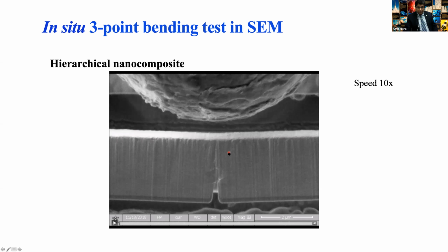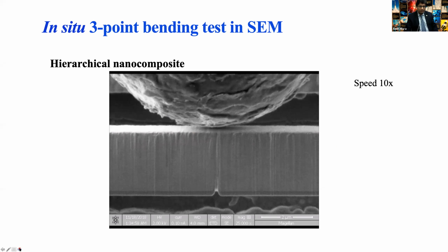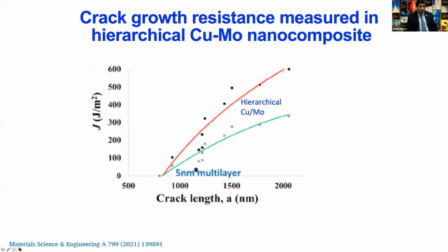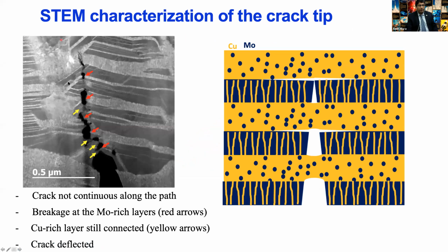So what we do is, when the test has stopped, because the sample did not fail, we section this with FIB and take the foil out and put it in TEM. That is shown in the next slide here. So this is one way where we can track it. This is how the crack progressed. And you can see as it is going from one microstructure to the other, how the crack opening is changed. And from here, you can discern what the possible strain energy release mechanisms are.